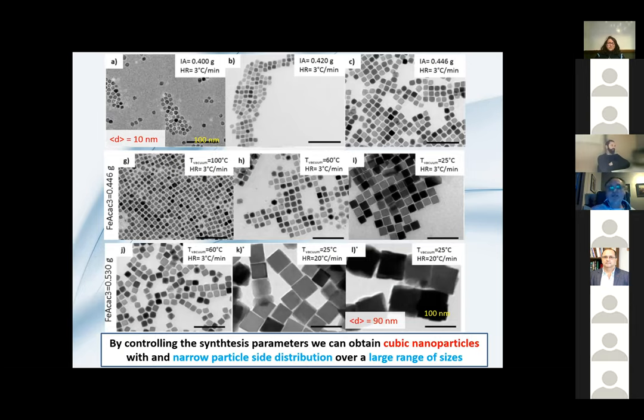And can we control the size? Well, yes. First, we did that using a standard technique, which is changing the amount of iron acetylacetonate. As you see, when we put in more iron acetylacetonate, we can get larger particles. The second approach we tried: usually before we start a synthesis, we degas the sample using a vacuum. Depending on when we do this vacuum, we can get different sizes. As you see here, if the vacuum step is performed at 100 C, we get small particles. But if we just pump the system at room temperature, we can get reasonably large particles.